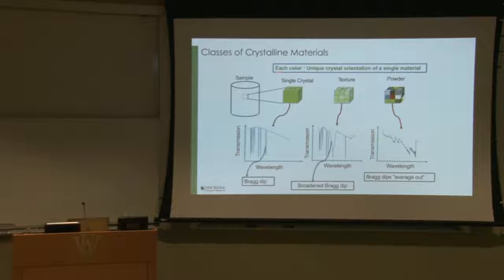If you have an object and you look at one small region, and that region is a perfect single crystal, and you measure the neutron transmission as a function of wavelength of just a small block, you can see that at certain orientations, the transmission just drops. Because the beam goes through, and because some part of it is crystalline, you basically have Bragg diffraction. Then you get a drop in the beam that goes right through because some of it is scattered either back or at some angle away. So this is what happens when you stick a single crystal in.